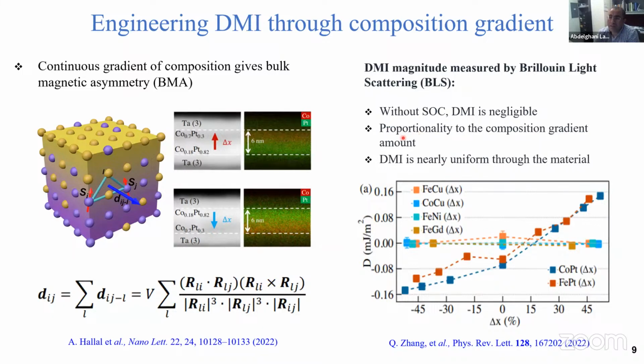The second important thing is that, in principle, this DMI is proportional to the composition gradient. I will define later what composition gradient means. That means if you increase the composition gradient, for example, we reach 50%, you can get sizable DMI, about 0.16 millijoule per meter squared. Also, DMI is usually uniform through the material. So that's why this kind of system is getting a lot of attention.